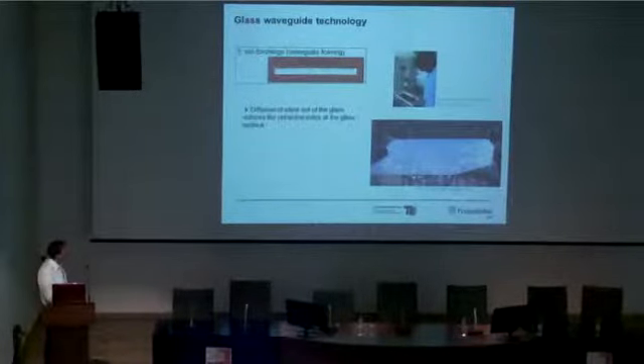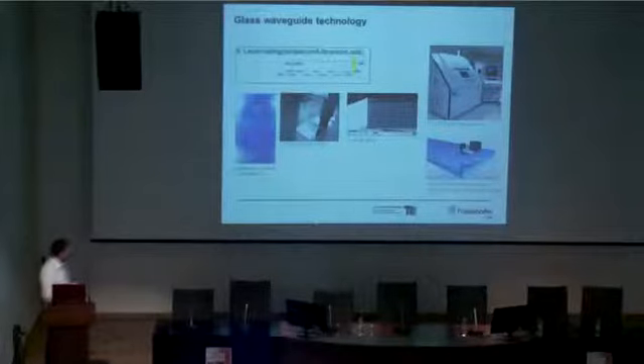And then we have a second lithography step, and in this step we can also save some features on the aluminium, because in this first aluminium etching step we can structure the aluminium for the waveguides, but also we can structure alignment markers, and these alignment markers have very high accuracy related to the center of the waveguides. So for post-alignment processes, it's recommended to use such alignment markers. And then we place it again in such a furnace with a different salt melt, forming the waveguide profile. And finally, we have to cut the panel to our final size.